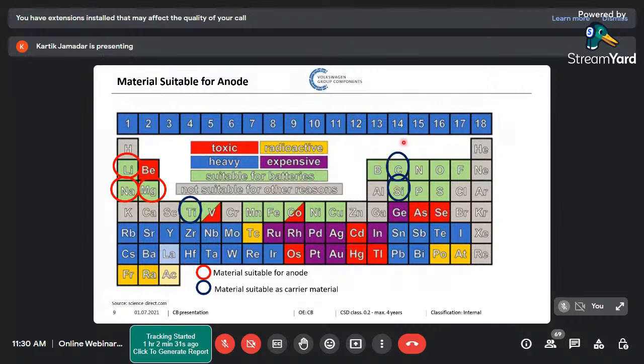On the other side, on the anode side, we have carbon in the form of graphite. The carbon, as I told you, has a problem that 6 carbon holds 1 lithium. It would be very interesting if we could find some material which can hold more lithium for the same amount of less mass. And there comes silicon. Silicon can hold 22 lithium for 5 silicon atoms. So you can imagine there is a drastic difference. It means the same amount of silicon can hold 4 times more lithium than carbon. So there is a lot of research going on on how to replace the graphite anode with a silicon anode.